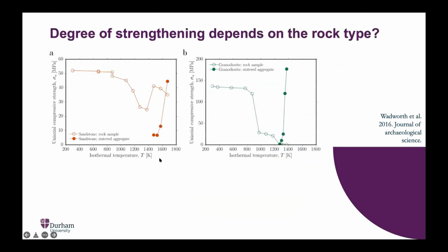So back to this diagram, this is in Kelvin. Sorry for mixing my units, but you can see that for the sandstone sintered aggregate, the temperatures of the fire are lower than the sintering process that would increase the strength. Whereas for the granodiorite, these temperatures where the strength increases so much are almost exactly the temperatures that we think these walls got to. So in the case of granodiorite, we think strengthening can happen really easily. And in the case of the sandstone, it would have had to be hotter than probably was possible. So we have a rock type control or a lithology control on our vitrification potential.